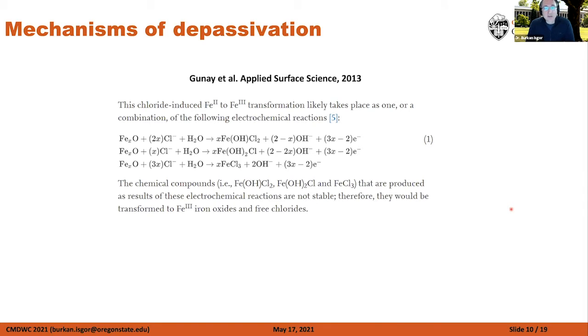At the end of that work, about 2013, 2015, we had an idea, again based on the literature. A lot of things that I'm showing on the slide are suggested from the 70s, 80s, where an oxide film, again, the form here is not important, but we know there's more of an Fe3 type of structure. Chlorides can form these species and take the iron out, and these iron chloride compounds are generally not stable in the solution, so chlorides actually release into the solution and come back and do this work again. So there is this understanding at this stage, but we didn't know exactly how this process took place.